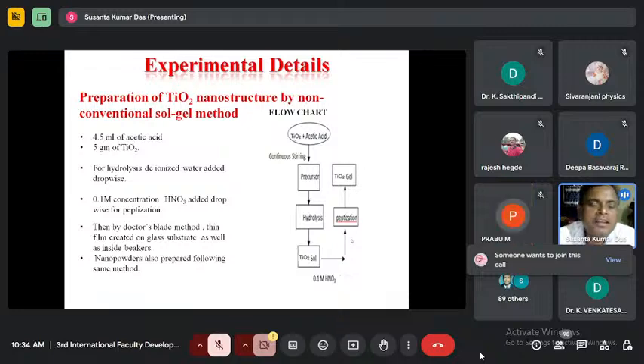Generally, when you go for creating any nanomaterials, let's say titanium dioxide nanoparticles, then you have to go for titanium chloride and other types of chemicals. Or if you are going for zinc oxide nanoparticles, then you have to go for precursors like zinc acetate or zinc nitrate. But those precursors are very much hygroscopic in nature, and they easily get deteriorated. Whereas these powders are very stable and their costs are almost similar.